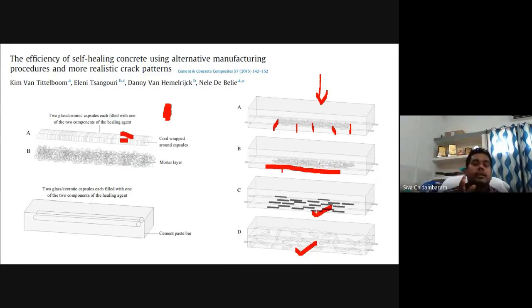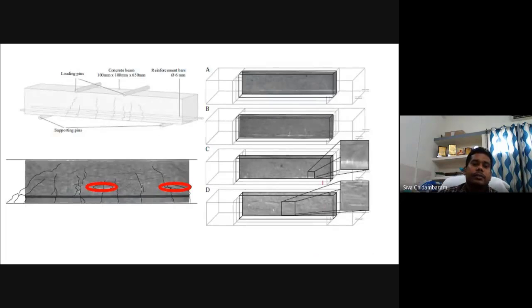So the epoxy or the adhesive will fill the crack internally. Once the epoxy has filled the cracks, the epoxy will try to set. There are two things. One, after reacting with the hardener, it can mature, or cure itself. Otherwise, some chemicals require ultraviolet treatment, or when the epoxy is exposed to the atmosphere, it will react with sunlight, and then it will mature itself. It will come to its curing temperature. Once the epoxy attains its curing temperature, it will start to mature itself. Otherwise, we have to apply a UV treatment. When you use UV treatment, the exposed adhesives will start getting cured, and it will become a hardened material that will create a bond between the cracked surfaces.